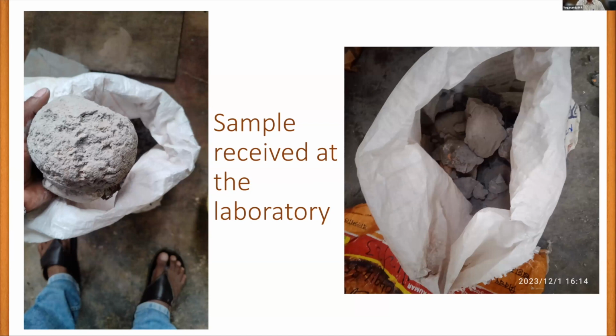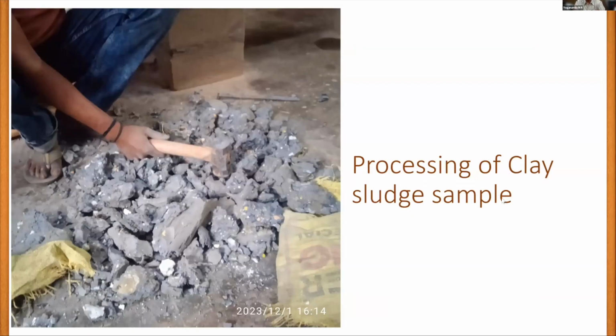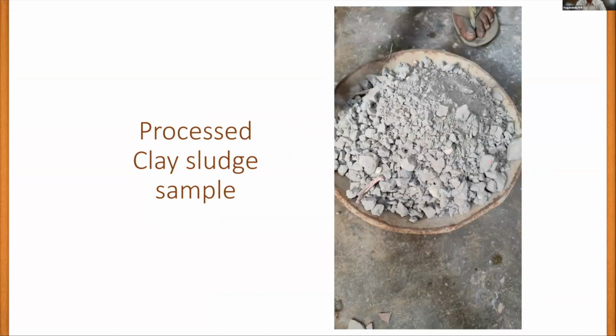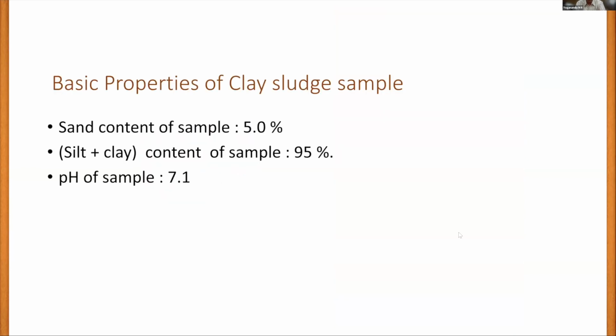You can see the next slide, which shows we need to break it using a hammer because it is so hard. Once we break them and process it to smaller size, we then had to put a lot of water so that it softens. The basic properties of the clay sludge sample: sand content, 5%,